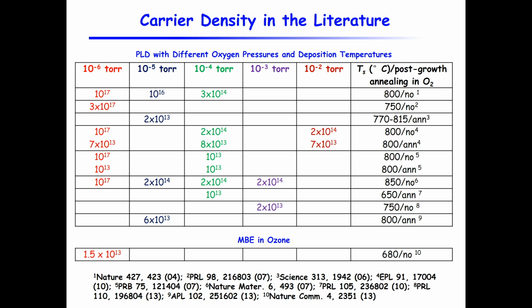So here I summarize the results in the literature. Here shows the oxygen pressure during the growth. Some of the papers have post-growth annealing, some did not. If you grow at really low oxygen pressure, you can see very high carrier density, which you know is not from the interface alone, but has oxygen loss in the substrate. If you have annealing afterwards, then you bring it down. Here it's 7 times 10 to the 13th.